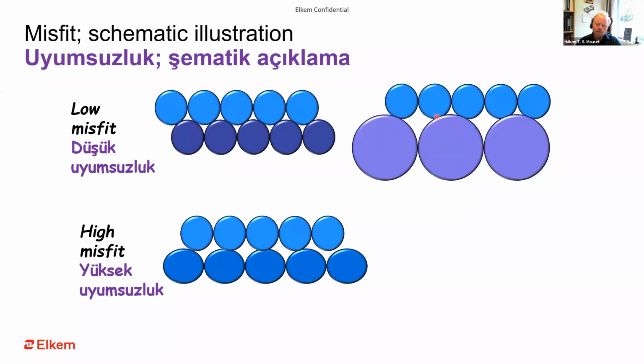But this is also an example of low misfit. We don't need to have particles that are exactly the same like we have here. Here we have particles with one diameter, and here we have particles which have a diameter which is a multiple of this diameter. So then we see that these fit quite well again. We have a repeating pattern. You see the same size and shape of the void between them.